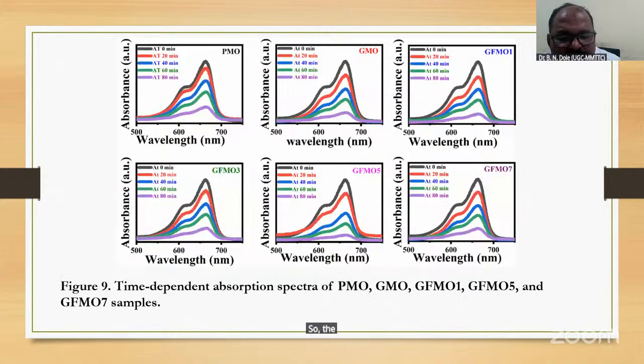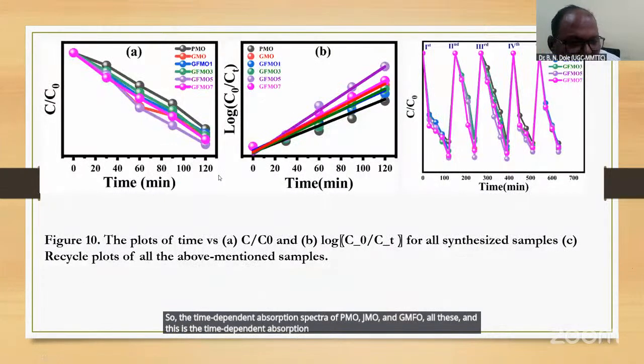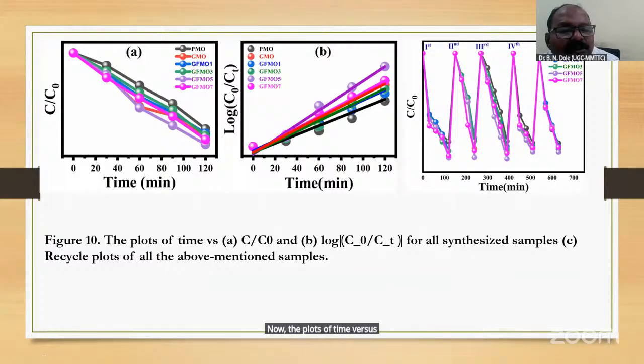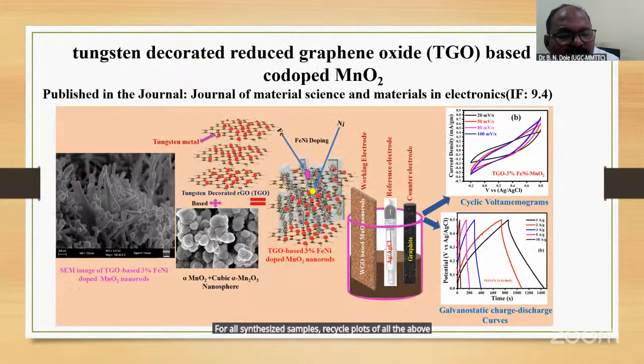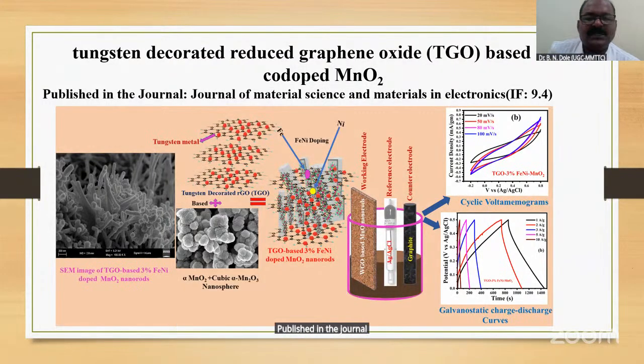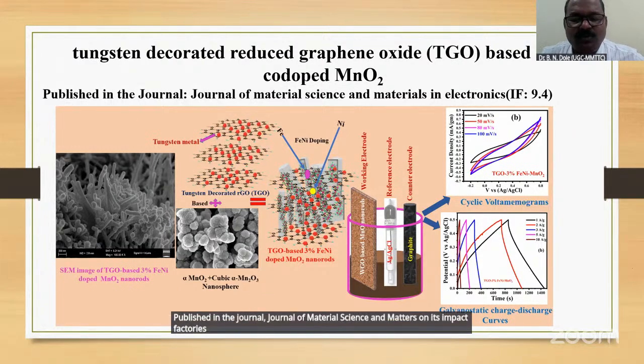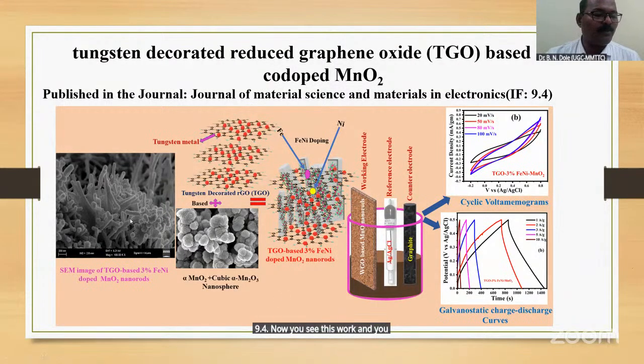So the time dependent absorption spectra of PMO, GMO, and GFMO, all these, and this is the time dependent absorption spectra. Now the plots of time versus C by C0 for all synthesized samples, recycle plots of all the above mentioned samples. The tungsten decorated reduced graphene oxide based iron nickel co-doped MnO2, published in the Journal of Materials Science: Materials in Electronics, and its impact factor is 9.4. Now you see this work, and you see here beautiful images of FESEM, and it is like nanowires. You see the powder material we have taken here, the thin films we prepared and taken its FESEM images.